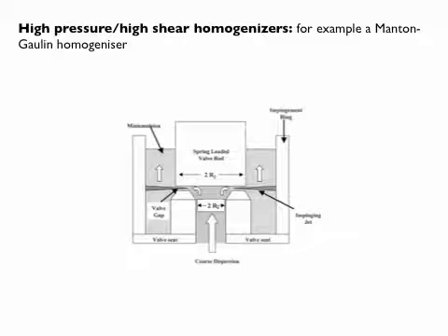Because the gaps are really narrow, you get all kinds of instabilities in droplets, because they get elongated. As a result, they break up. Again, this is also very high power, because the pressure drop across the system from the center to the left is massive. Yeah? And if you recycle this a few times, you can go from a coarse emulsion to a miniemulsion.